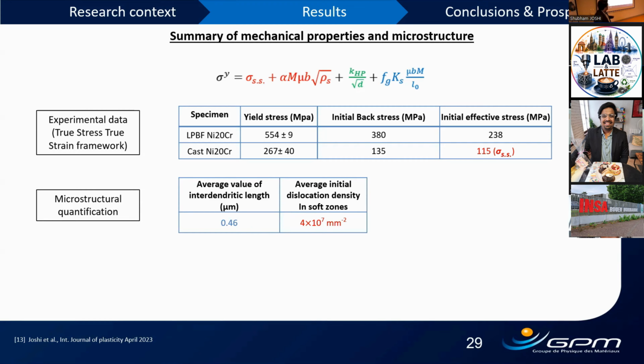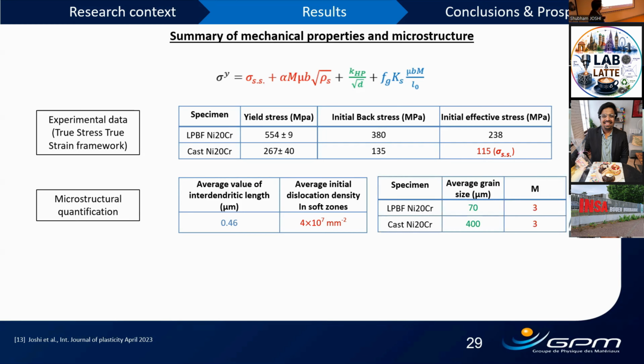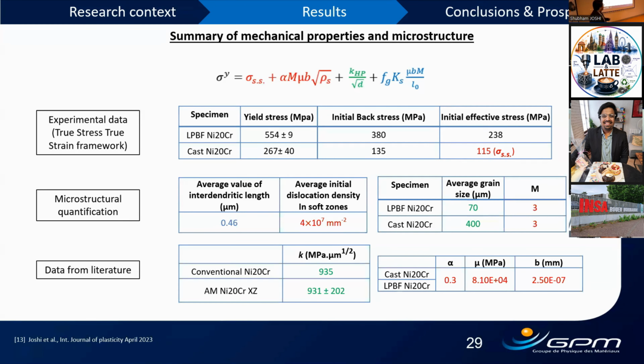Average cell size can be calculated from microstructural characterization. Same with the initial average dislocation density in soft zones. Average grain size and Taylor factor can also be extracted from EBSD analysis quite easily. And finally, there are some parameters like the Hall-Petch constant, alpha, which is the dislocation arrangement parameter, shear modulus, and Burgers vector, which can also be extracted from literature. Two parameters I did not mention: Fg is the fraction of grains which have hard zones. We believe that these dendritic structures are present in all the grains, so it has been considered to be 1. And Ks is a constant which depends on stacking fault energy, which can also be extracted from the literature.